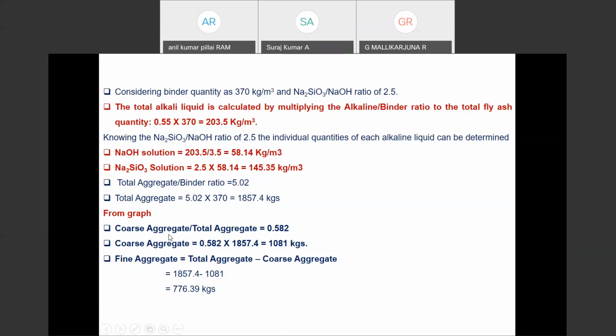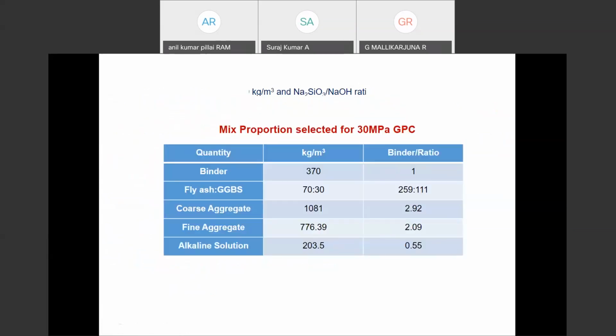And from the curve we have drawn, the coarse aggregate to total aggregate ratio, we will get as a value of 0.582. From that you are going to get the coarse aggregate. Once we want to get the fine aggregate, total aggregate minus coarse aggregate, you are going to get the fine aggregate there. Like that, whatever quantities you require based on your estimation, you can select the different quantities of mixes. For that, the mix proportion we had selected as 30 MPa.